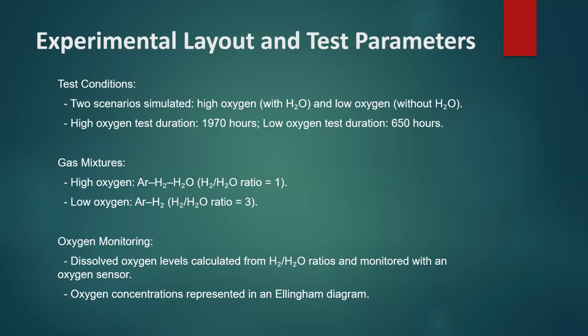For the gas mixture, in high oxygen conditions the argon hydrogen H2O ratio equals 1, and for low oxygen the argon hydrogen ratio equals 3.